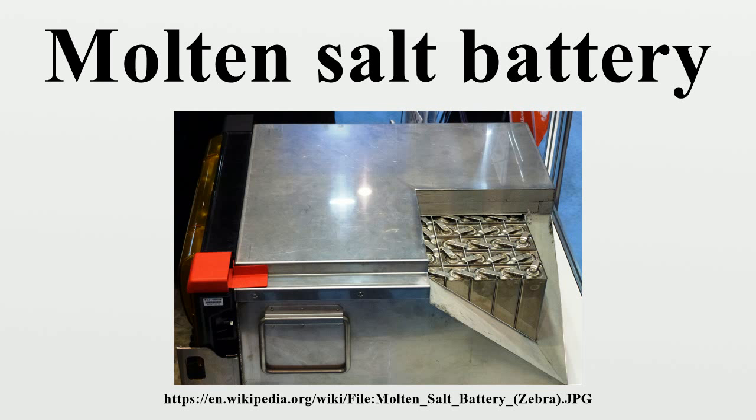Sodium-sulfur: The sodium-sulfur battery, along with the related lithium-sulfur battery, employs cheap and abundant electrode materials. It was the first alkali metal commercial battery. It used liquid sulfur for the positive electrode and a ceramic tube of beta-alumina solid electrolyte. Insulator corrosion was a problem because they gradually became conductive and the self-discharge rate increased. This problem of dendritic sodium growth in NaS batteries was addressed in the development of the Zebra battery in 1985.